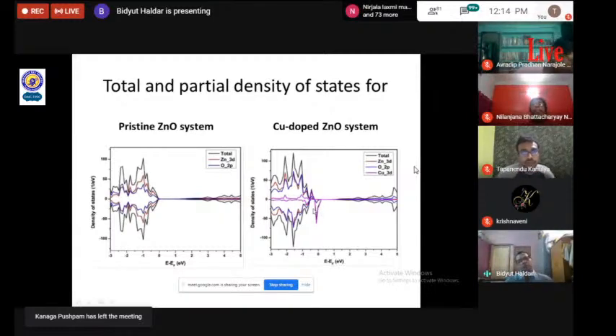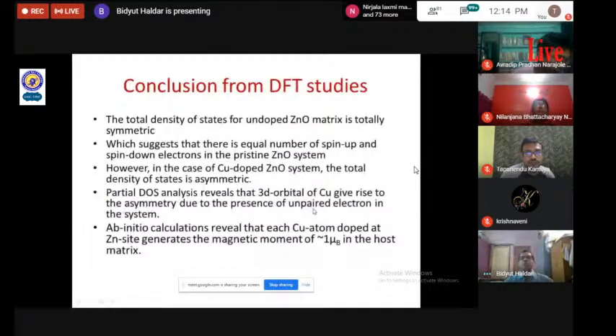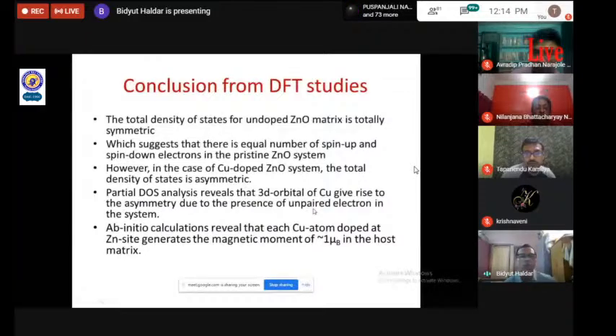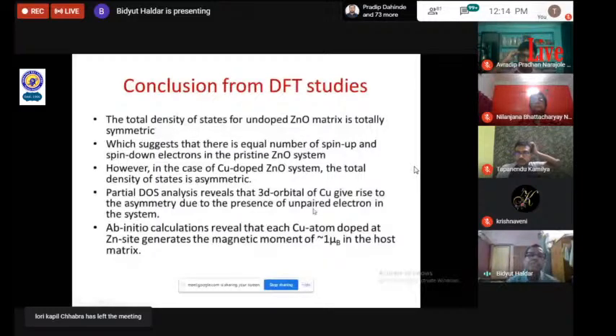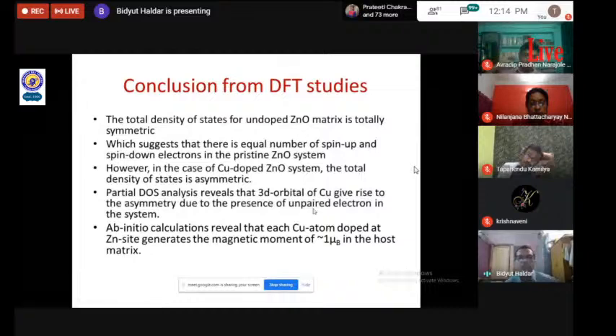A brief conclusion from the DFT studies that we already did was that the total density of states for the undoped zinc oxide matrix is totally symmetric, which suggests that there is an equal number of spin up and spin down electrons in the pure zinc oxide system. However, in the case of the copper doped zinc oxide system, the total density of states is asymmetric. Partial density of states analysis reveals that the 3d orbital of copper gives rise to the asymmetry due to the presence of an unpaired electron in the system.